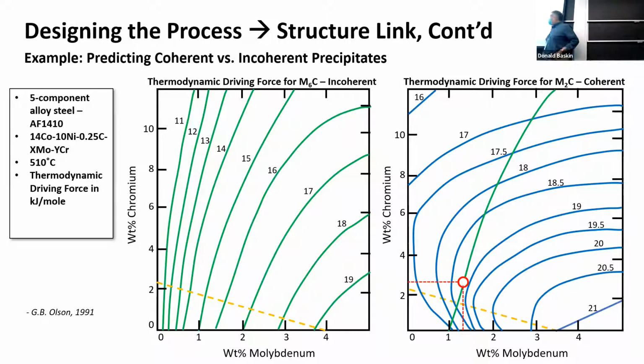two graphs that I copied out of Greg Olson's work. I redrew them, but they're actually his work. Originally, these were directly out of Thermo-Calc, but I just redrew them in PowerPoint because they're easier to read. And this is a graph of weight % chromium versus weight % molybdenum. So choosing how much molybdenum, how much chromium you're going to put in your steel, what's going to give you the highest strength. You want to choose these compositions so that you maximize the driving force for making M2C carbides and minimize the driving force for forming incoherent M6C carbides. Make sense?